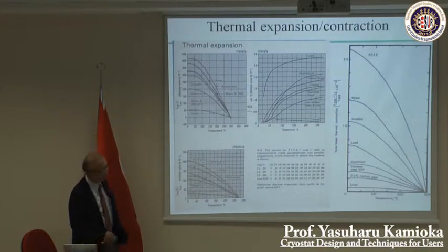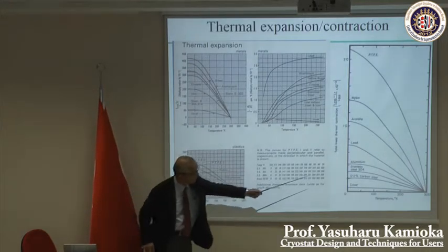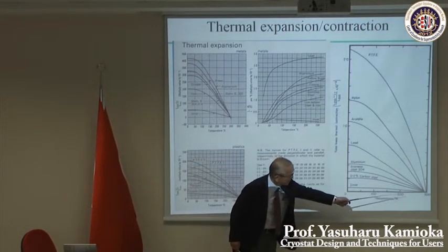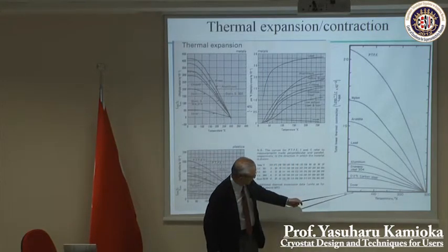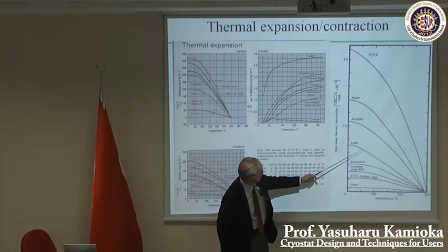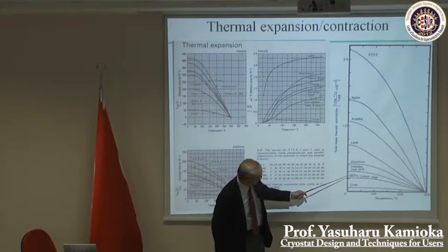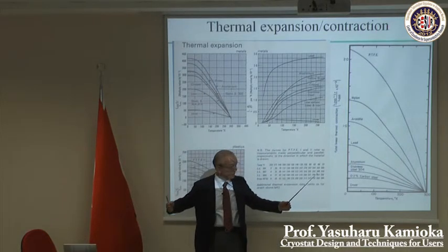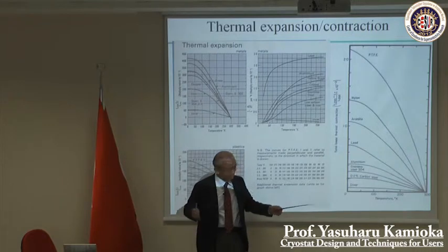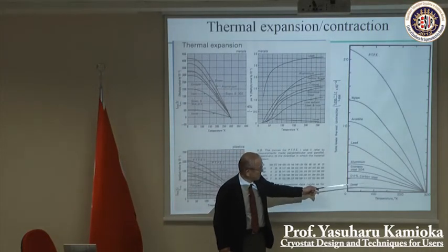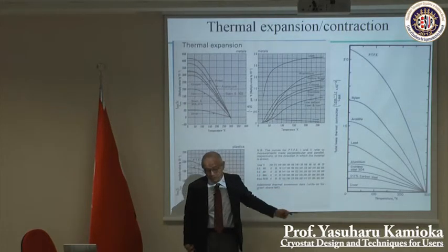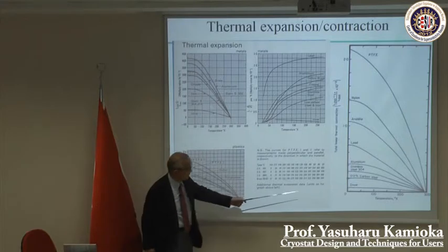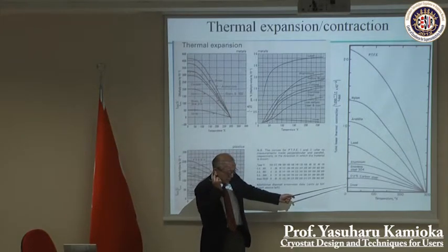Also the expansion and contraction. I usually use this figure, this one. When you go from 300 Kelvin all the way down to 100 Kelvin, a stainless steel bar of 1 meter length contracts about 3 millimeters, 0.38% of reduction. But Invar, this is a 36% nickel iron.